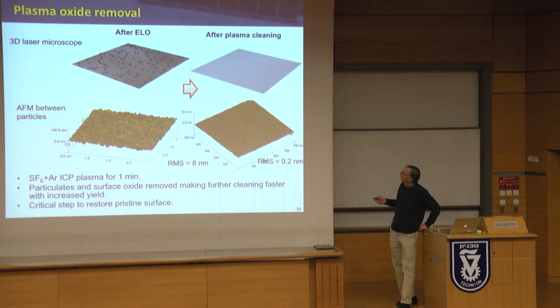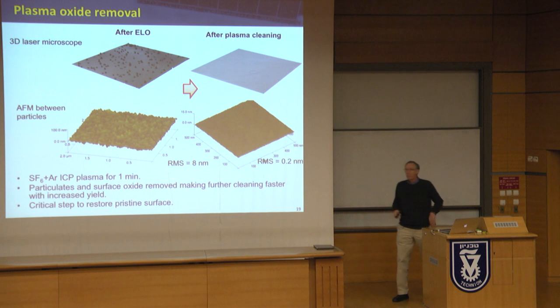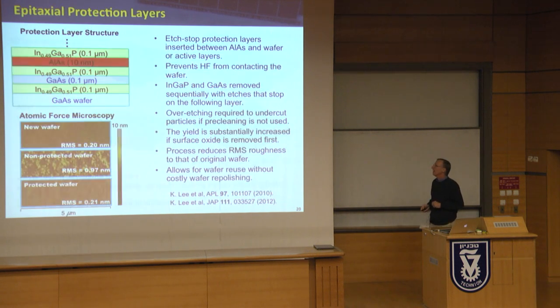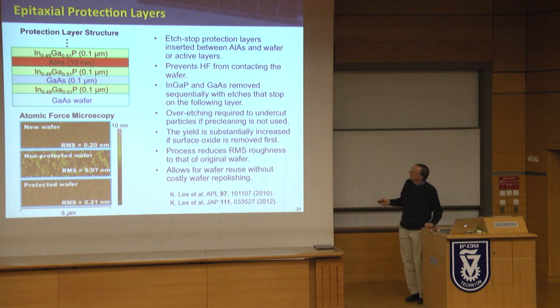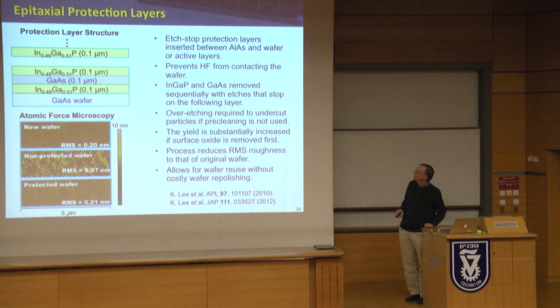We use a little plasma, this is a inductively coupled plasma of sulfur hexafluoride, just to clean it up. This is still not good enough. You can see it really loses the roughness, and we get back to smooth plates. But now we're on indium gallium phosphide. So we have the indium gallium phosphide. We've taken off the aluminum arsenide. That's the sacrificial layer. And we're left with this.